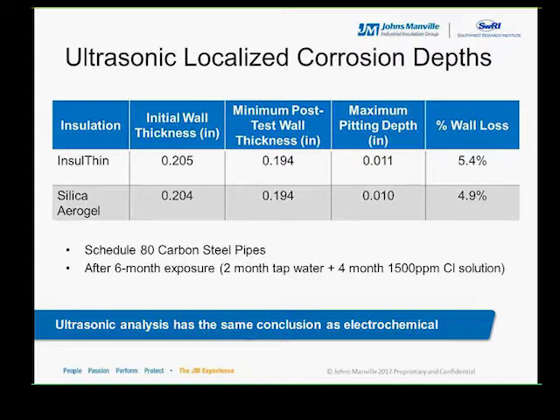The initial thickness of the pipe sections was about the same at 0.205 inches, and both pipes had a minimum post-test wall thickness of 0.194 inches. So if you do the math by subtracting the minimum post-test wall thickness, which is in that second column, from the initial wall thickness, which is in the first column, you can calculate the maximum pitting depth, compared in the third column. And what we see is that the ultrasonic method, with both pipes, they were statistically the same in regards to corrosion pitting.